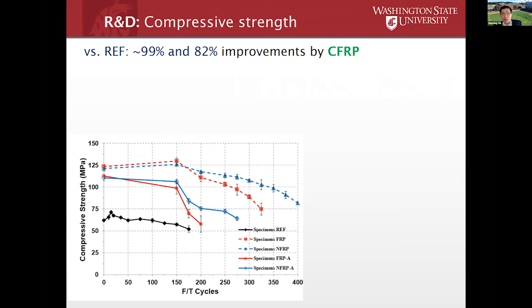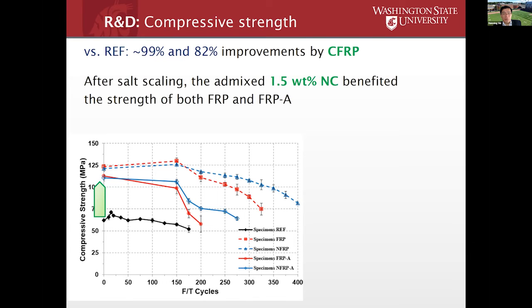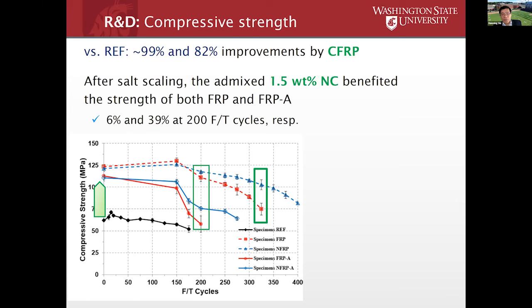Now, starting from compressive strength, one interesting thing is that once we confine the cylinders with FRP, of course, in this case, we are seeing increase in compressive strength because of confinement. It's about 99% or 82% improvement by the FRP for the new and pre-aged concrete respectively. And then after salt scaling, the 1.5% nanoclay really benefit the strength of both the new concrete wrapped by FRP and the pre-aged one. The benefit was 6% and 39% at 200 freeze-thaw cycles respectively. And now once you further expose it to more freeze-thaw cycles, then the benefit of nanoclay is even more pronounced.